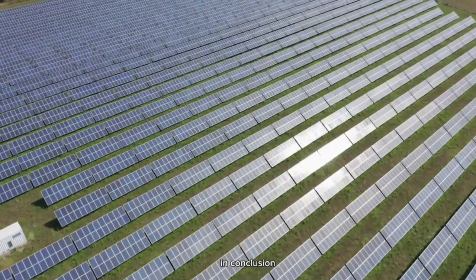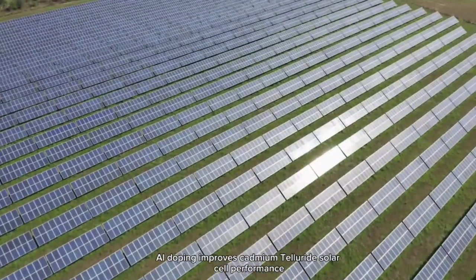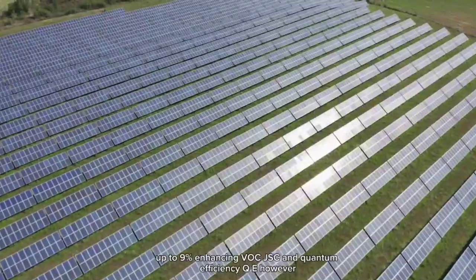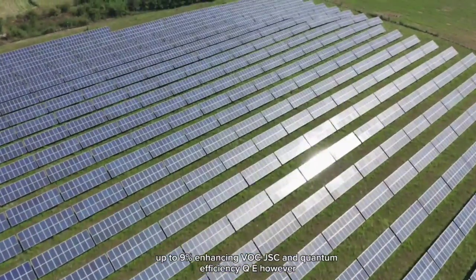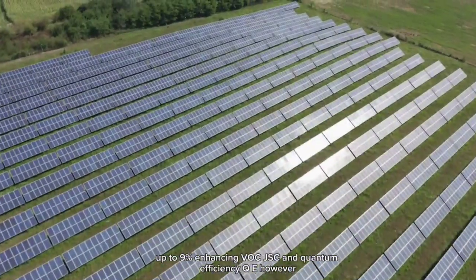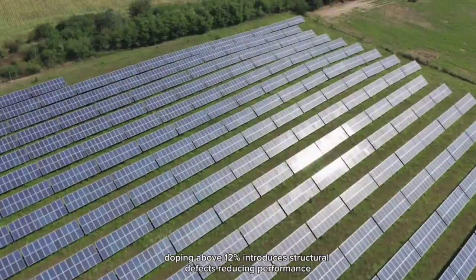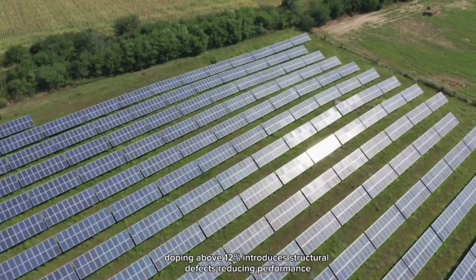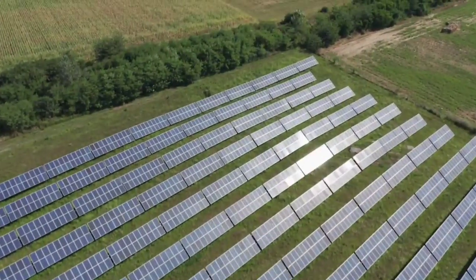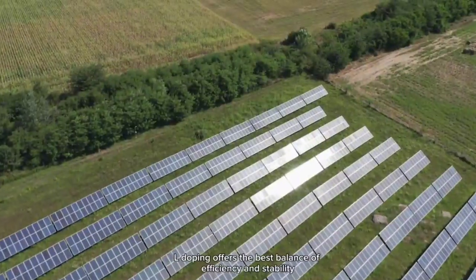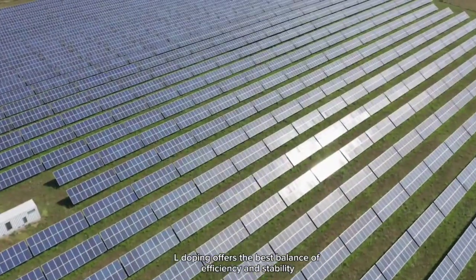In conclusion, Al doping improves cadmium telluride solar cell performance up to 9%, enhancing VOC, JSC, and quantum efficiency, QE. However, doping above 12% introduces structural defects, reducing performance. 6% to 9% Al doping offers the best balance of efficiency and stability.